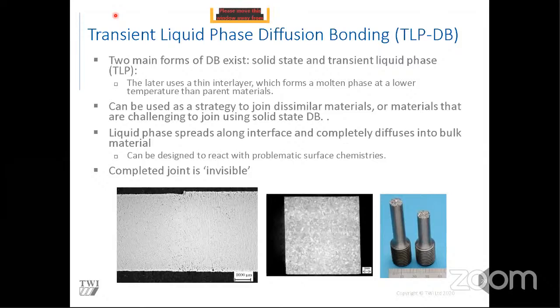So talking of oxide layers and interlayers, I'm going to spend one slide talking about a process called transient liquid phase diffusion bonding, or TLPDB. This is slightly different to solid state diffusion bonding because we put a thin interlayer of material between the two parts we're trying to join, and this will form a molten phase at a lower temperature than the parent materials. So essentially we're trying to melt the interlayer but not the parent material. It's kind of like brazing in a way, but you're applying pressure and load to the part, and you can get away with much thinner interlayers.